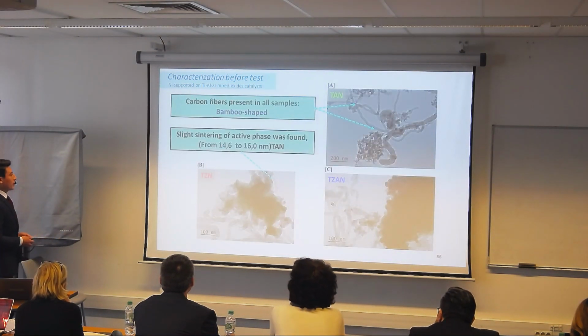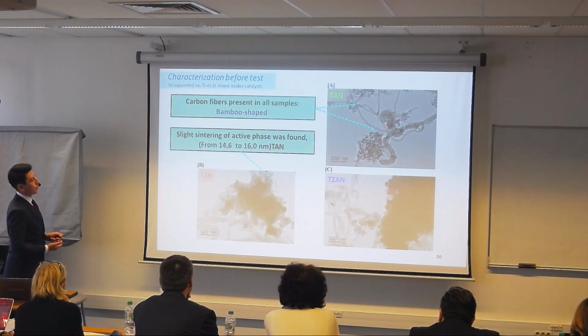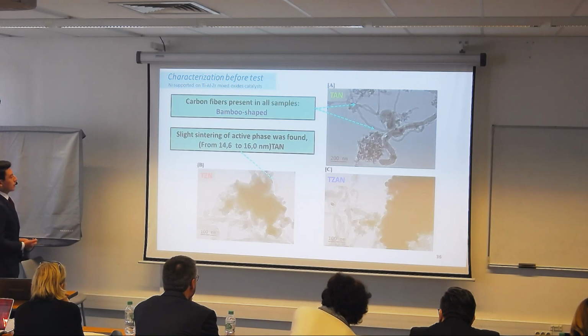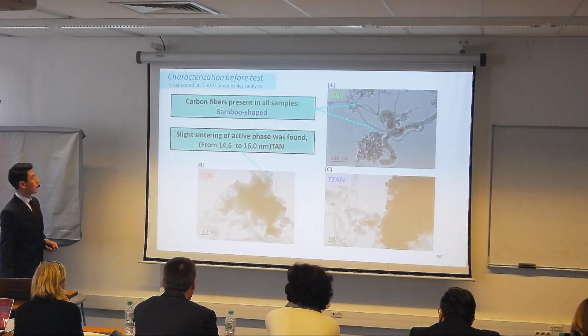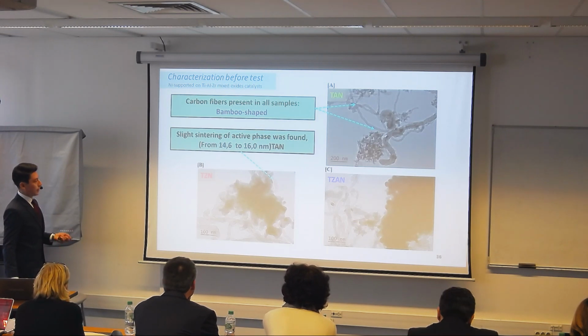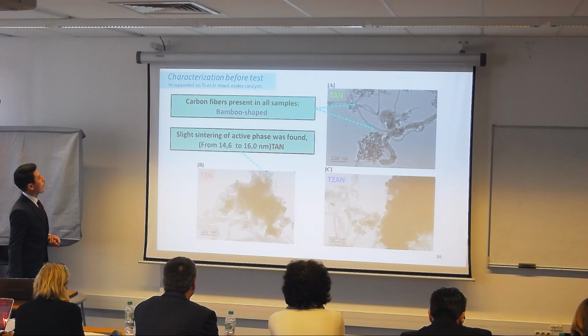Another very interesting thing that we find is that the carbon that I just mentioned before is formed in a bamboo-shaped way. We can see in this that for every catalyst we have all these very interesting kinds of nanotubes, and we have a very slight sintering happening for the active phase.